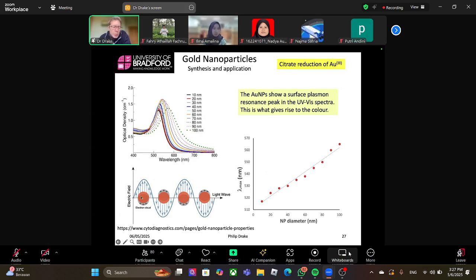The SPR peak comes from the electrons on the particle surface. Metallic particles are in a metallic conduction band. As the wavelength of light passes over, the electron cloud can be distorted above and below the particle. That's the transition you're measuring when you're looking at the SPR peak.